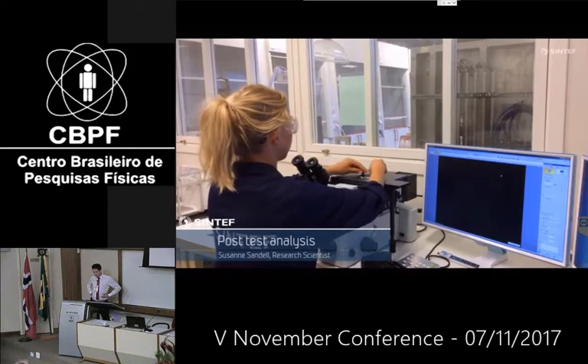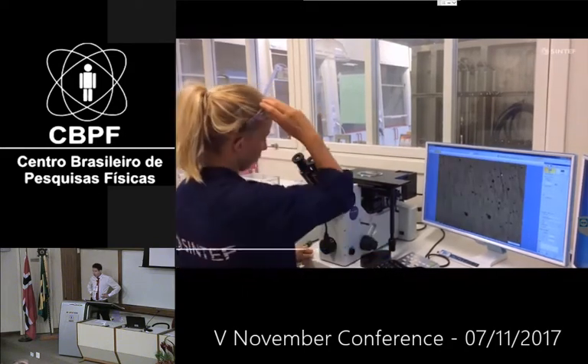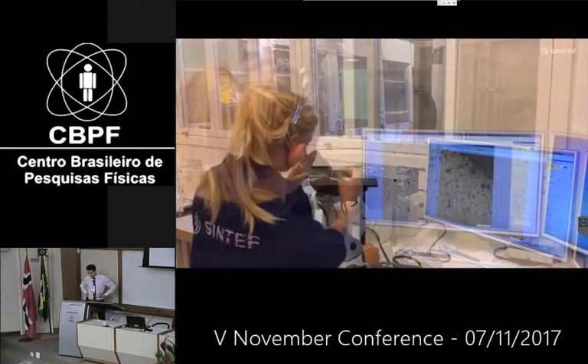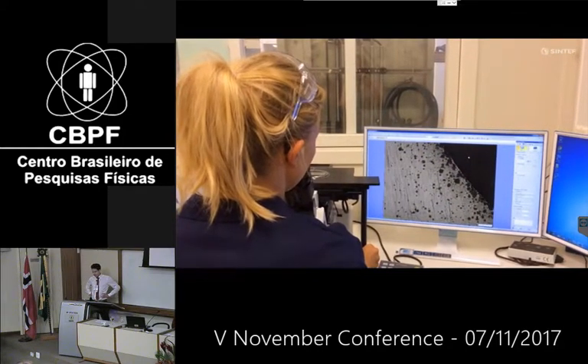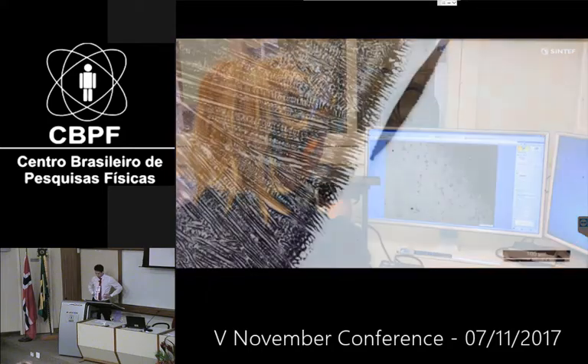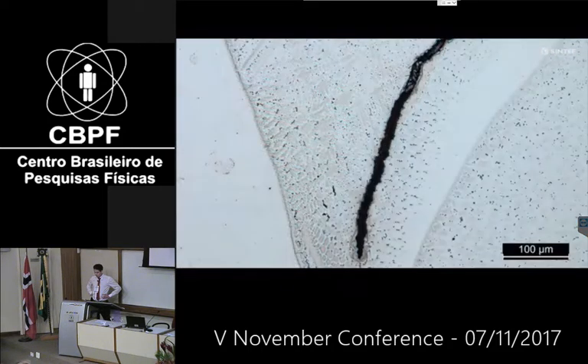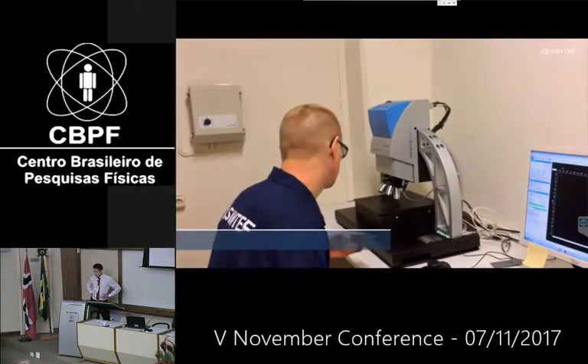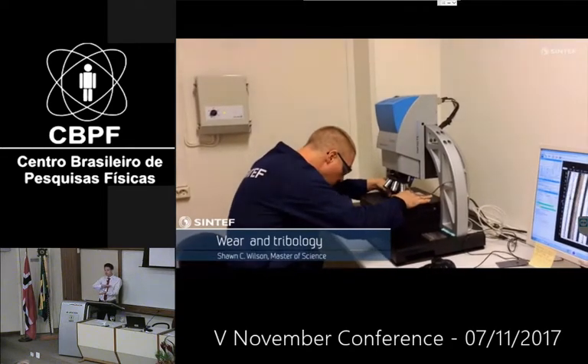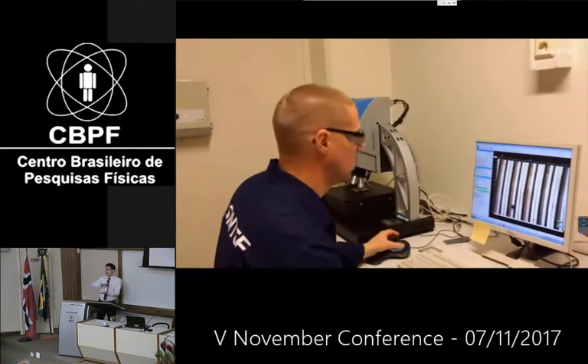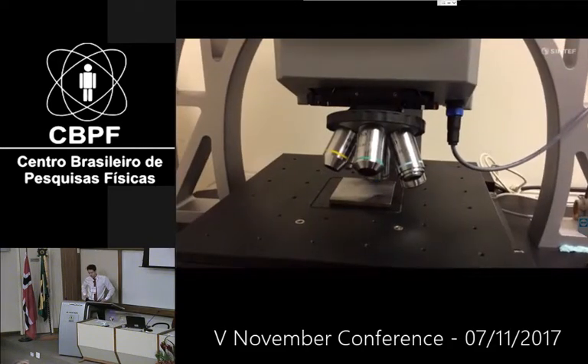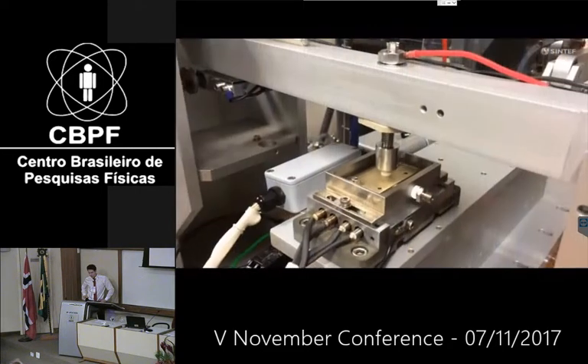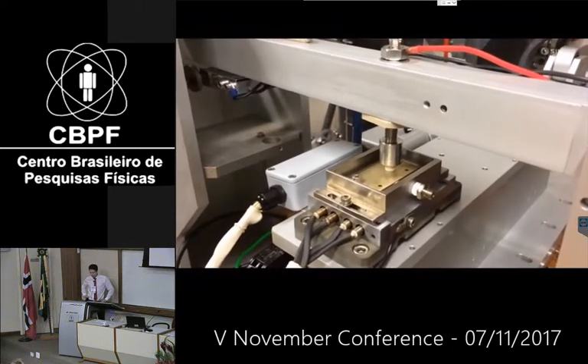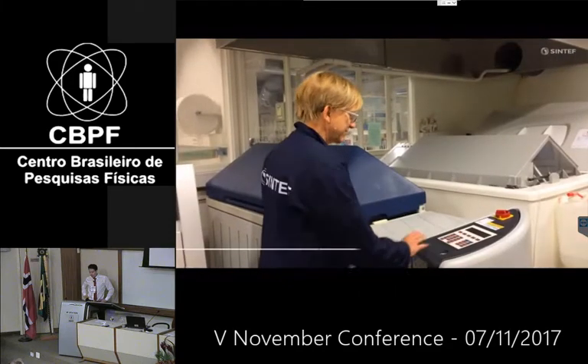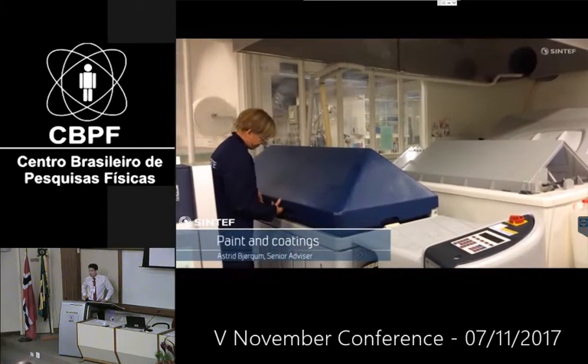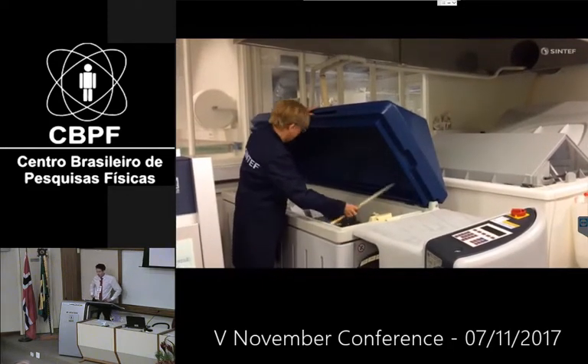And here we have post-test analysis of the samples. Do we have cracking? How is the substrate after exposure? Here we have a crack in a weld. And here we have a confocal microscope imaging a surface with topography through a layered imaging technique. Scanning over the surface. That's very good for pitting, for example. We also have tribology and tribocorrosion laboratory and climate chambers for paint and coating delamination with and without cathodic protection.